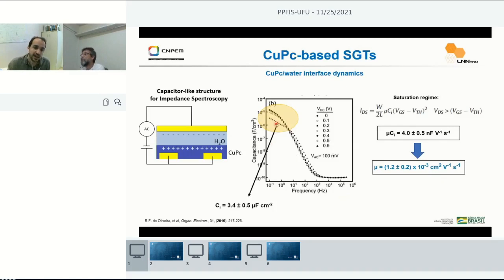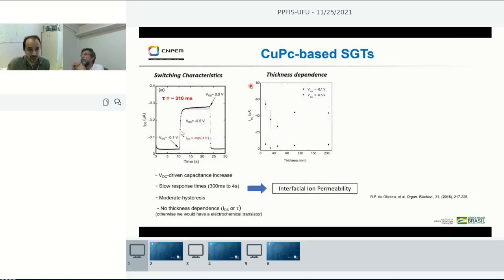As I mentioned, we observe that we do not reach a plateau, and we also have an increase of capacitance by applying a DC bias. This phenomenon was quite curious to us. We also observed that if we measure the current as a function of time and switch on the device, it is quite slow to switch on and reach an on-state current. We extract quite high switching times, around 300 milliseconds for the formation of the electrical double layer.